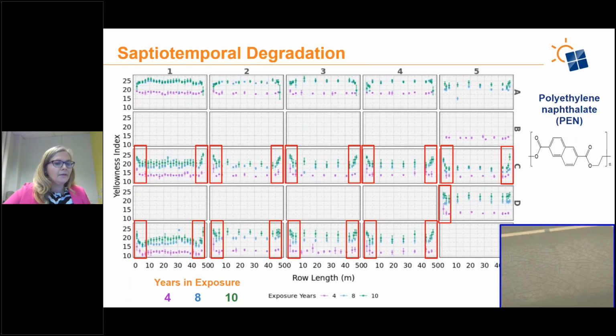One thing we saw here is that at the same site and at multiple other sites, we still see this edge effect. You can see it here outlined in these red boxes, and it continued through time. This is 4, 8, and 10 years of exposure. We still continue to see an increase in yellowness index.